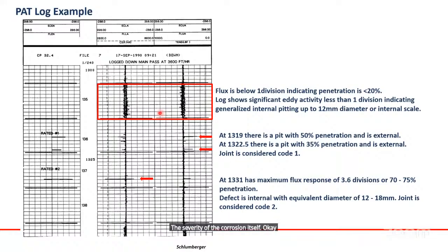At 1319, there is a pit of 50% penetration, and it is external, because the flux gives 50 and the inner gives 0. At 1322.5, there is a pit with 35% penetration, and it is external. The joint is considered code 1, according to the table.